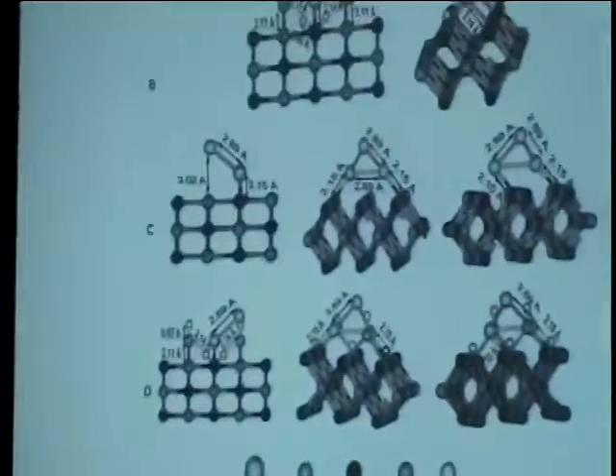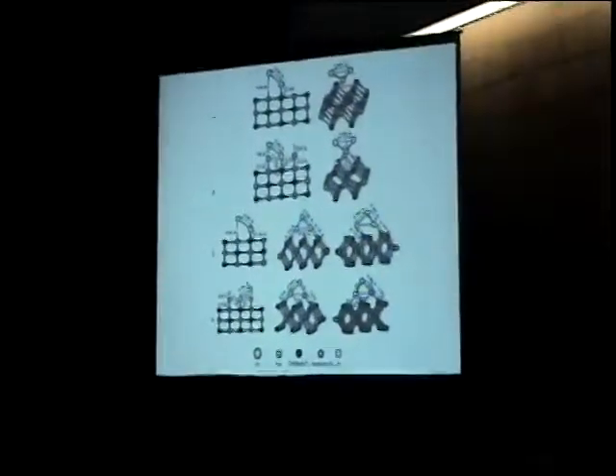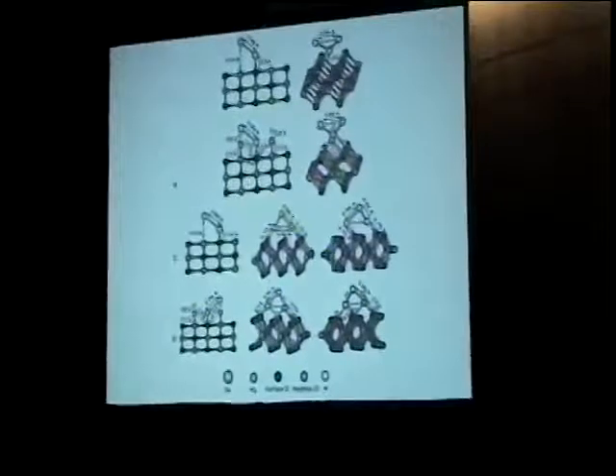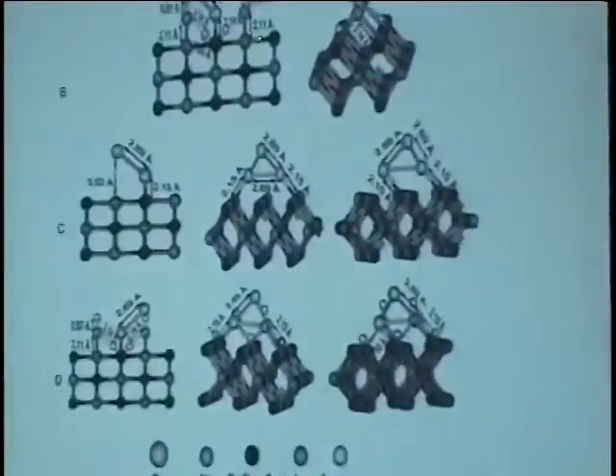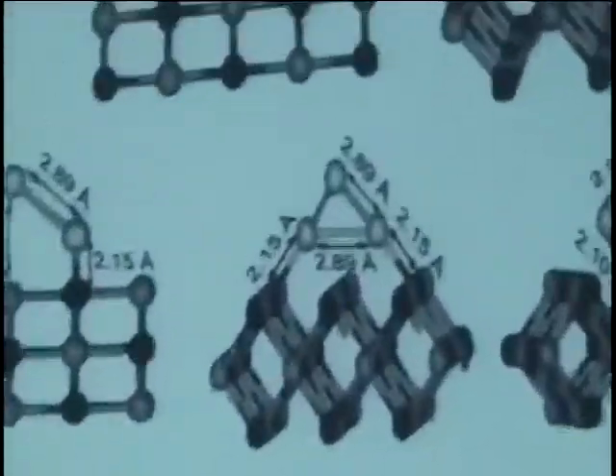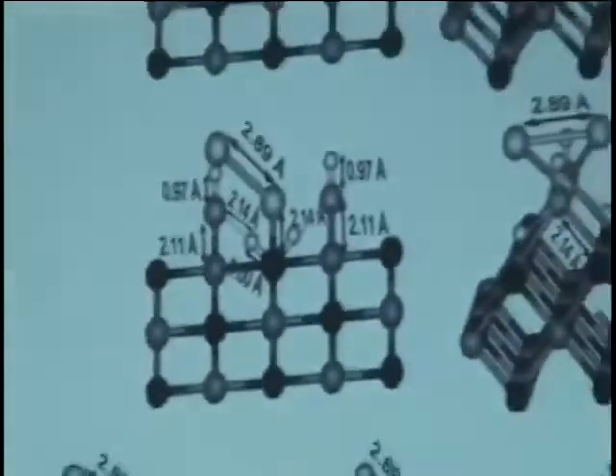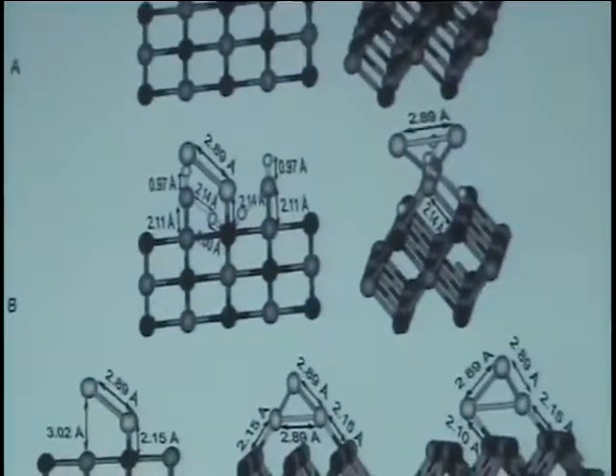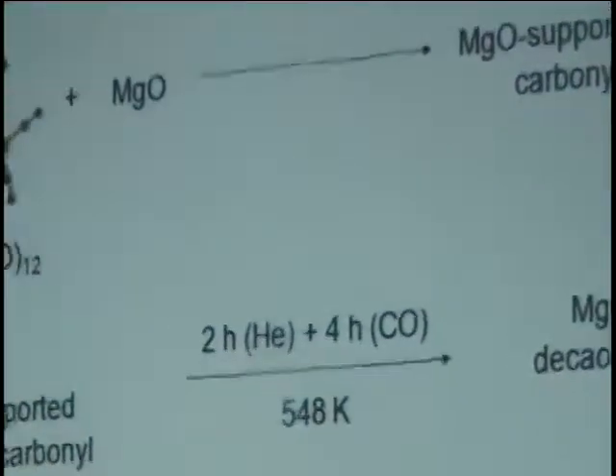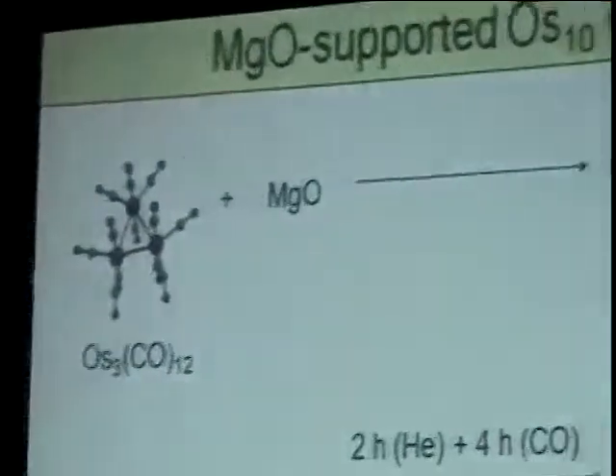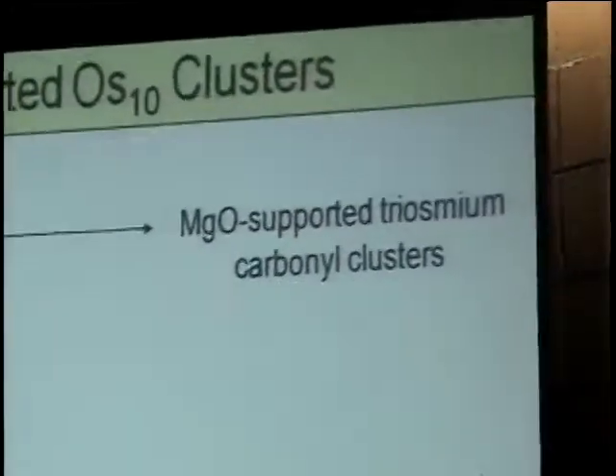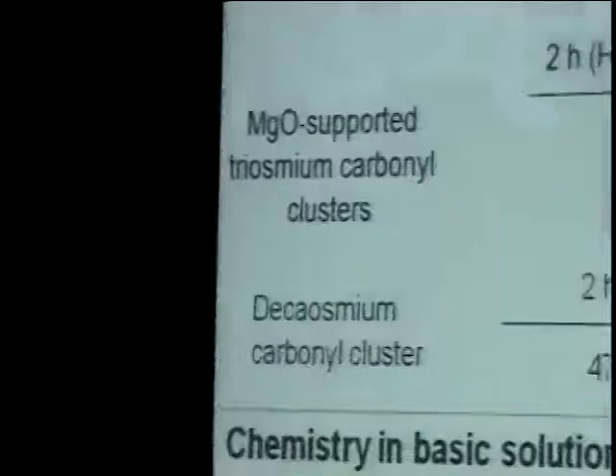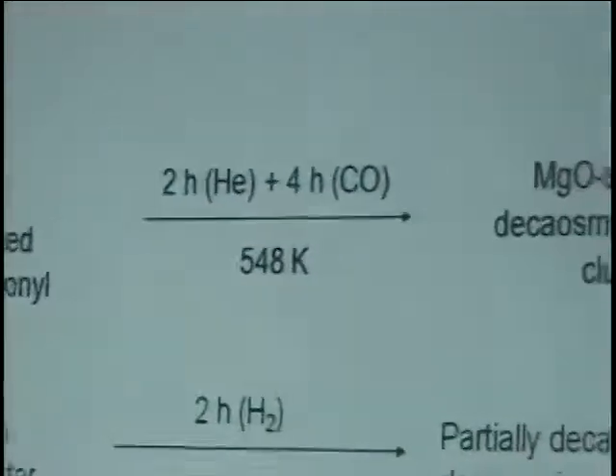And so what one is doing here is simply using the results of the microscopy in constraining the osmium-oxygen distance, there you see it in this model, to be in the range of that determined by the X-ray spectroscopy for the average samples. Okay, let's go to now slightly larger clusters. I'm watching the clock. There's two nervous people sitting next to me.